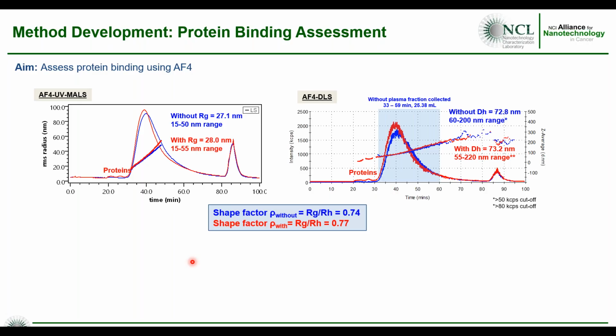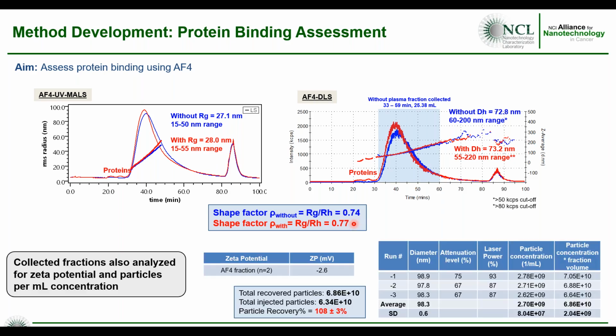We also can do protein binding assessment with LNPs, similar to what I showed you before with the Doxil, Onivyde, and AmBisome. So we took these LNPs, incubated with human plasma, ran it through AF4, calculated the shape factor, and they're roughly the same, implying that there is no protein binding to the surface. Also, the shape factor gives you an idea of the mass distribution. So this tells you there's something in the interior of the LNP because the shape factor is roughly 0.77.